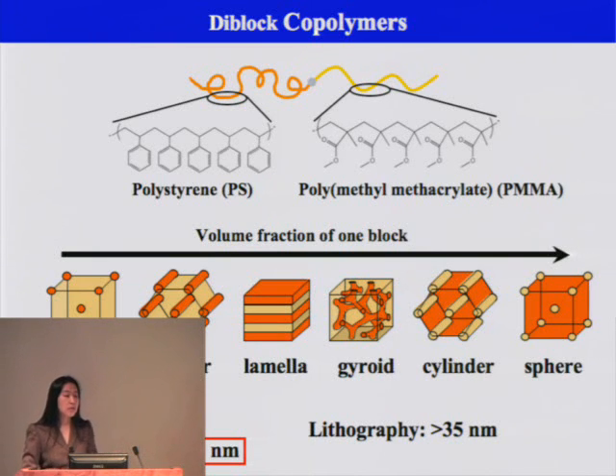Especially if you work with E-beam lithography, you will see that you can get very well controlled patterns, but it's painstaking. If you want to do 1 millimeter by 1 millimeter, it can take a fairly long time. With lithography, the dimension you get is probably going to be hard to go below 35 nanometers reliably.